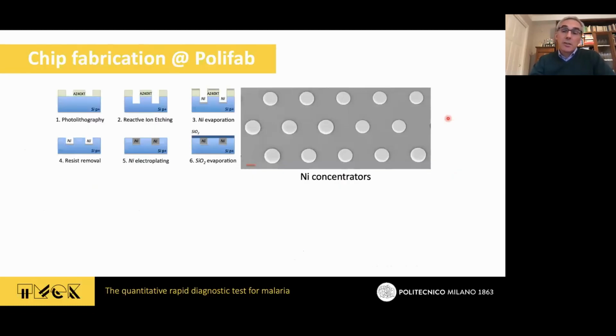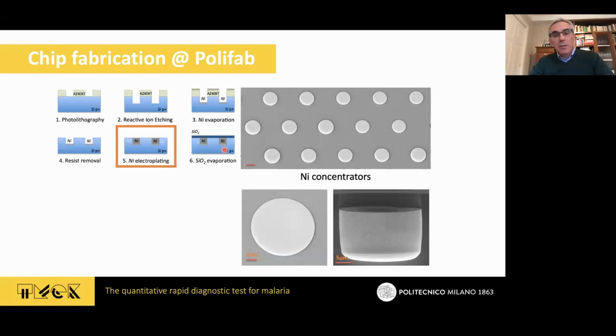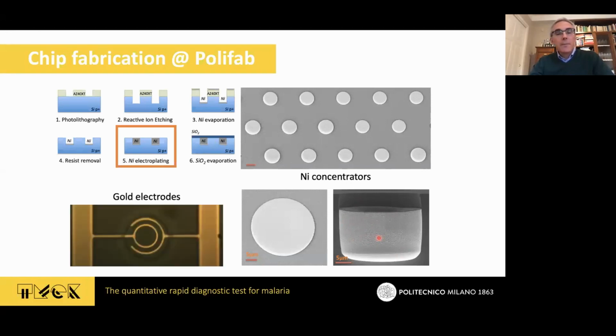Now what about fabrication? We are using typical clean-room fabrication. We embed our nickel concentrators in a silicon microchip by drilling holes by reactive ion etching, and filling them by electroplating. At the end, we planarize the chip and we deposit some silicon dioxide to separate the magnetic layer from the electrode. The critical problem for us was the electroplating, but we solved it, and you see some steps in the filling of these holes in the silicon. And finally, you see that we fabricate gold electrodes directly on top of the nickel concentrator with this annular shape, fitting the round shape of our concentrators.